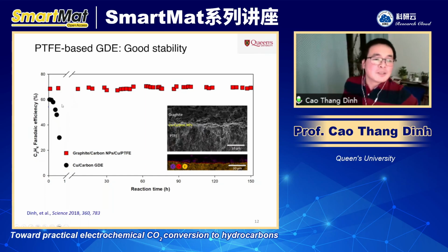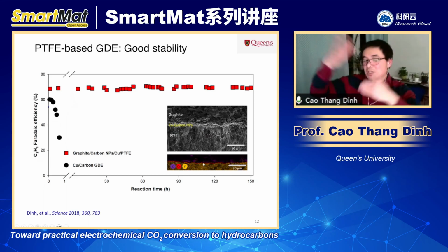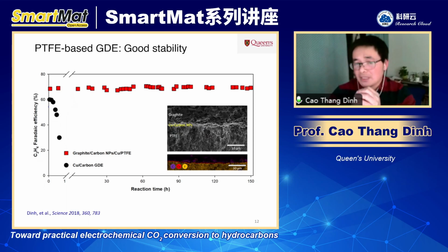Now, in comparison to the carbon, as you can see here, the black symbol, it dropped within an hour. And also, we looked at the substrate after the reaction, just to see why. It's not so clear, but we can still see the copper layer sandwiched between the carbon and the PTFE layer. So it worked great in terms of stability.